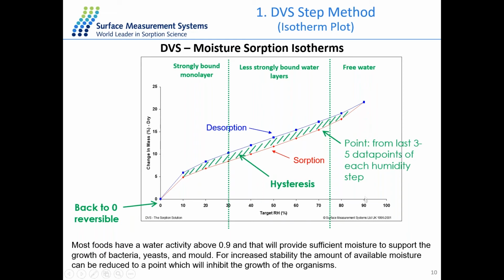So the same at 90% RH, a 20% change in the mass, which means this sample is going through a bulk sorption dominated mechanism, compared to some surface sorption of a low uptake sample. And the desorption is going back to 0, meaning a perfectly reversible process. As you can see, there is a little gap between sorption and desorption, and this is called the hysteresis gap. This is because the molecules during the desorption process move from the bulk to the surface, and it's a diffusion limited process, so it will give some different kinetics compared to the sorption branch. And this will cause the hysteresis between sorption and desorption.